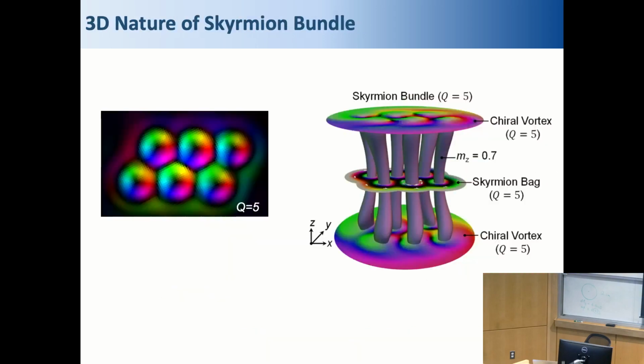But I will say that there is still some three-dimensional structure. So this is our simulation. Inside, it's what we expected. There are some skyrmions wrapped by a helical link. But on the top and the bottom surface, the central skyrmions melt and end up with this chiral vortex. And this is exactly a realization of this picture.